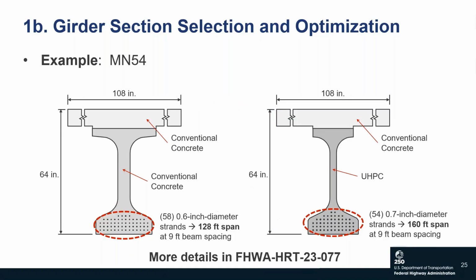If we add a conventional concrete cast in place deck on each section, the conventional concrete beam on the left, UHPC here on the right, and for the UHPC section, if we use 0.7-inch diameter strands instead of the 0.6-inch for the conventional concrete, we can increase our span length from 128 feet for the conventional concrete section to 160 feet for our UHPC section. So we can see we can increase our span length by about 25% while maintaining that 64-inch depth.